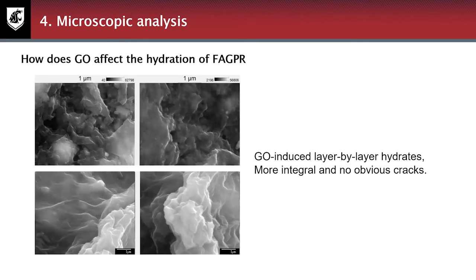So how does GO affect the hydration of geopolymer? Here, we run the SEM analysis, and we found that GO induced layer-by-layer hydrates. So this means the hydration is more integral, and we didn't detect obvious cracks on this SEM.